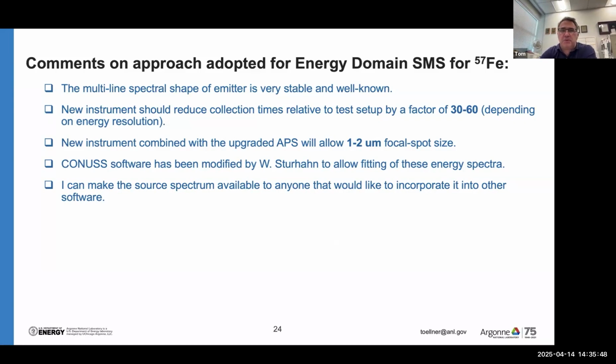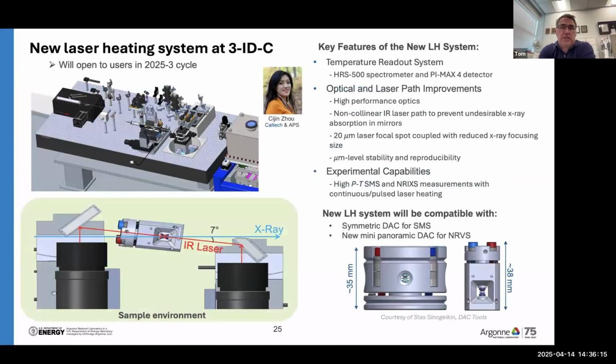The new instrument should reduce collection times relative to the test setup by a factor of 30 to 60, depending on the line width of the source. And the upgraded instrument will also have a 1 micron focal spot size. CONUSS software is available for fitting the spectra. And if people prefer to use other software, of course, I can provide the source spectrum as needed. Just email me.